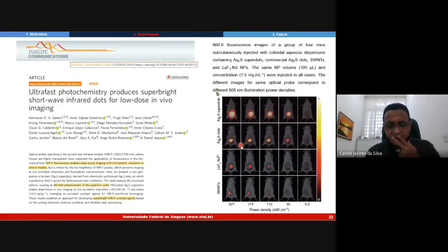In this picture here, we compare luminescence images using commercial silver sulfide dot, neodymium-doped lanthanum fluoride nanocrystal, and single-walled carbon nanotube. Okay, silver sulfide superdot enables deep tissue in vivo imaging at low excitation intensity, lower than 10 milliwatts per centimeter squared, and low doses, lower than 0.5 milligram per kilogram. Imaging has a heavily bright contrast agent for infrared window preclinical imaging. These results establish an approach for developing super bright infrared window contrast agents based on the synergy between chemical synthesis and ultra-fast laser processes.